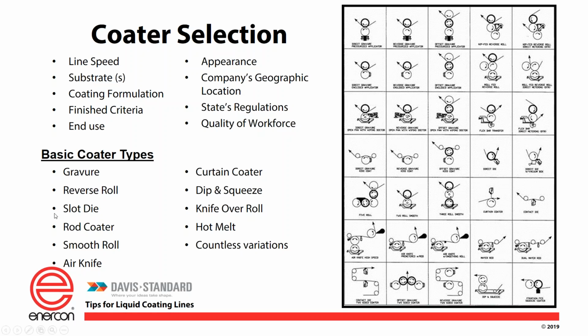Curtain coaters are fairly newer in the industry. You need to be formulated to run these. You can't take existing coatings in most cases and apply them. But what this will do is apply, let's say, for these label products, your adhesives. And it's about 6 inches above the web. It'll drop your adhesive onto a moving web at speeds above 400 feet a minute up to 3,000 feet a minute. The advantage is I'm not touching the substrate. I'm not abrading it. We don't get any streakings or buildups. And it also gives you the same thickness of coating in the peaks and in the valleys.